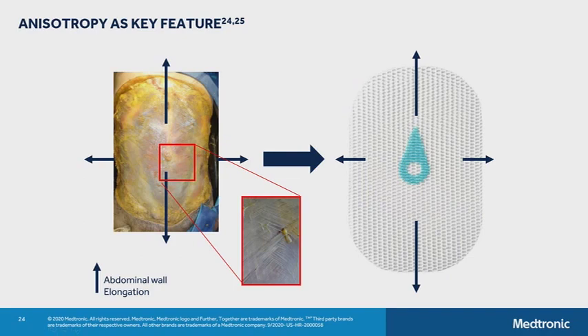So we've described how we manufacture mesh and how they have warp and weft directions. It shouldn't be a surprise to you that these different directions can have different mechanical properties. Now, our meshes are anisotropic by design, specifically our ventral meshes. With internal data and clinical data, we have set standards for these properties to ensure that the textiles work effectively if they're placed in either direction, though. In the ventral space, meshes are designed to have more deformation in the cranial-caudal direction and more strength in the transverse direction to match what's going on in the abdominal wall.